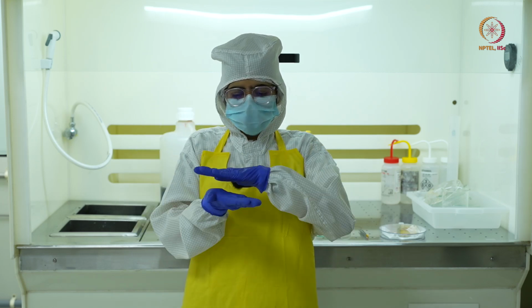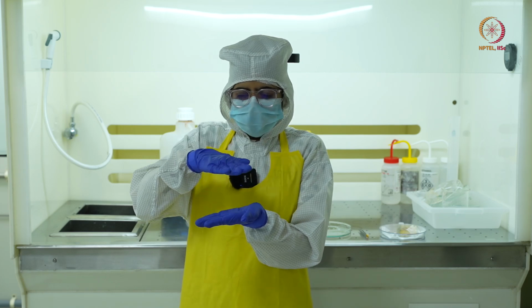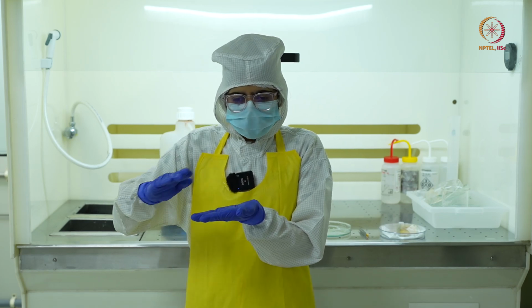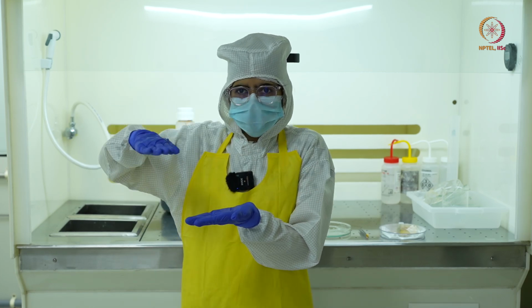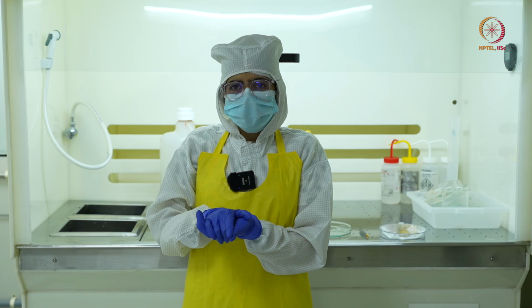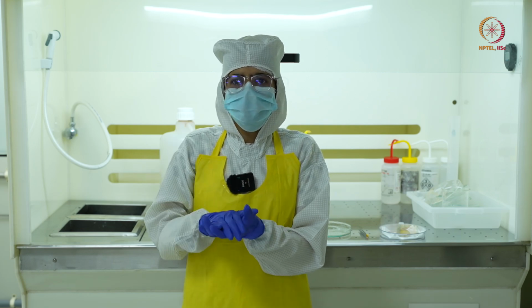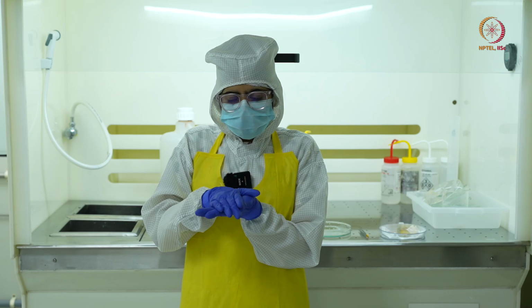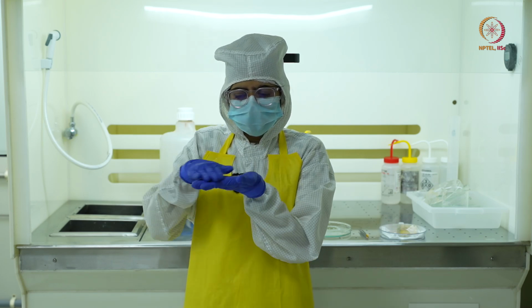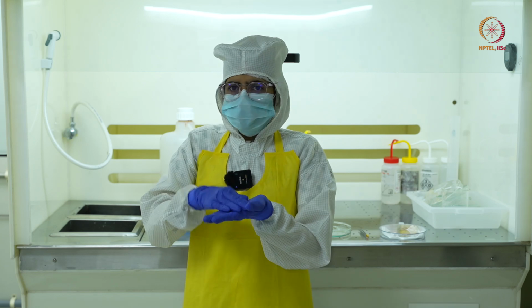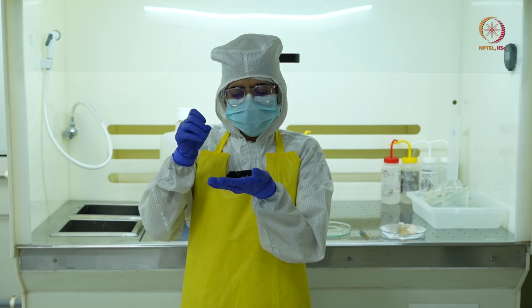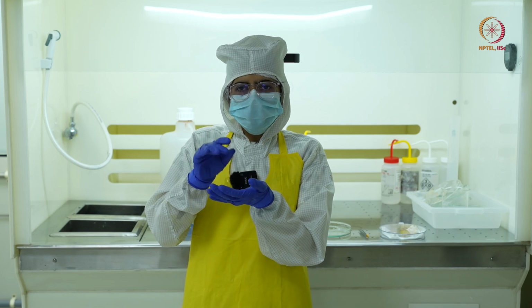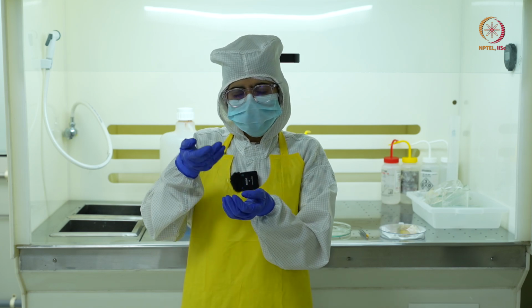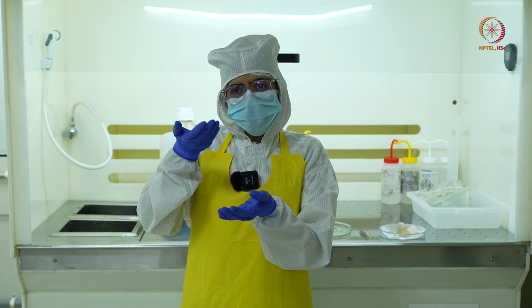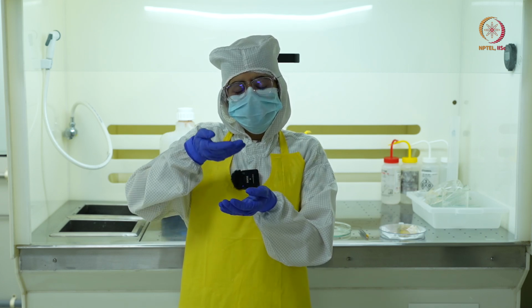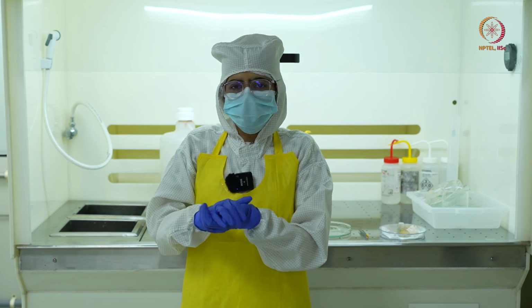So we'll have a substrate. On top of that, somewhere there is photoresist, somewhere it is plain wafer, and on top of that we have a blanket deposition of metal. This lift-off technique is used when we don't have an etchant to etch the metal. So what will happen when we put this substrate or this wafer into acetone? Acetone is a photoresist stripper. So acetone will go inside the metal, and it will take out the photoresist. So when it takes out the photoresist, the metal will also automatically come out along with the photoresist.